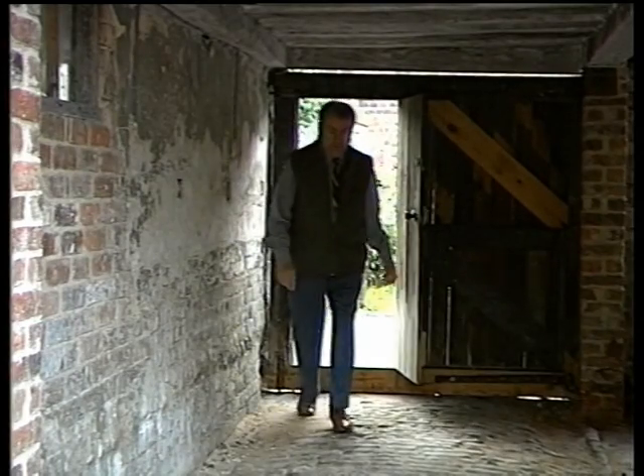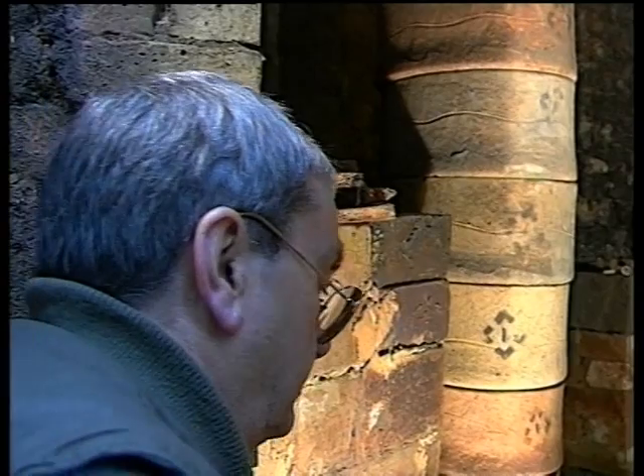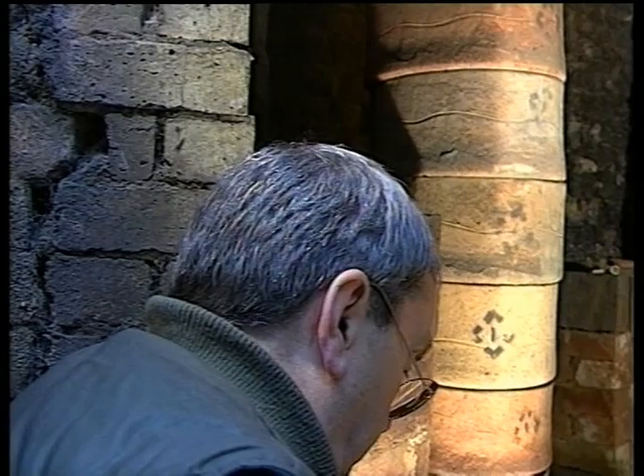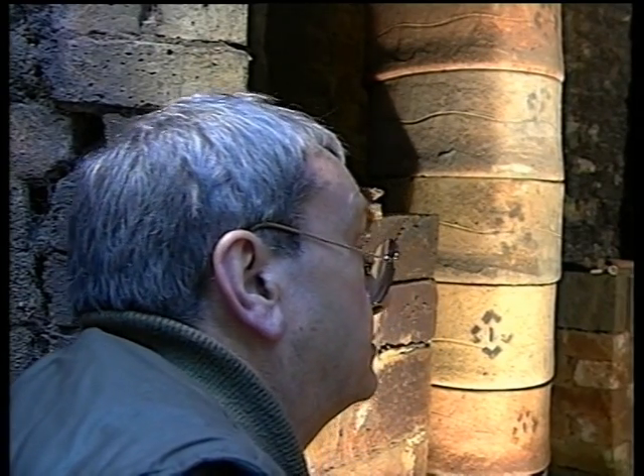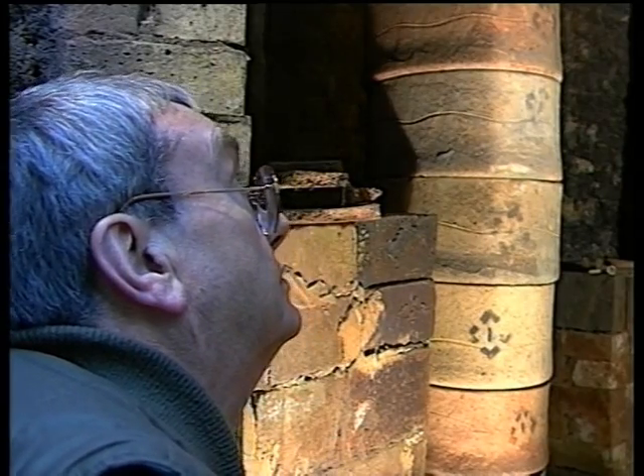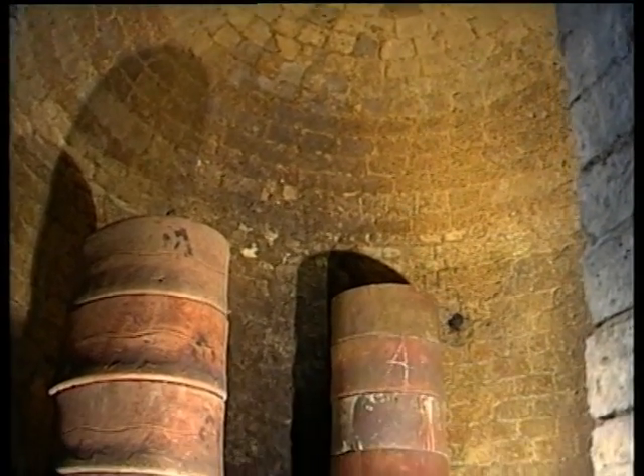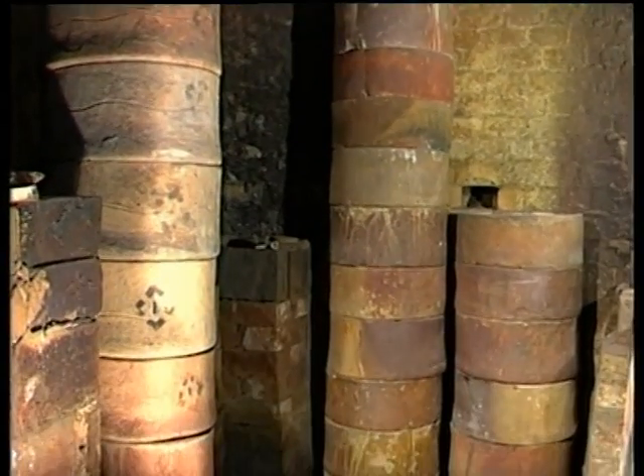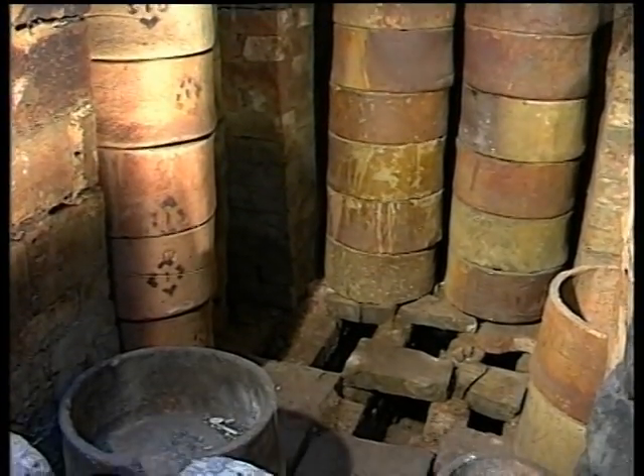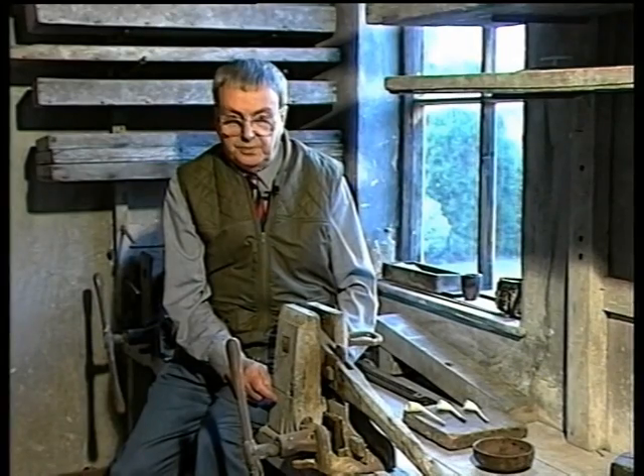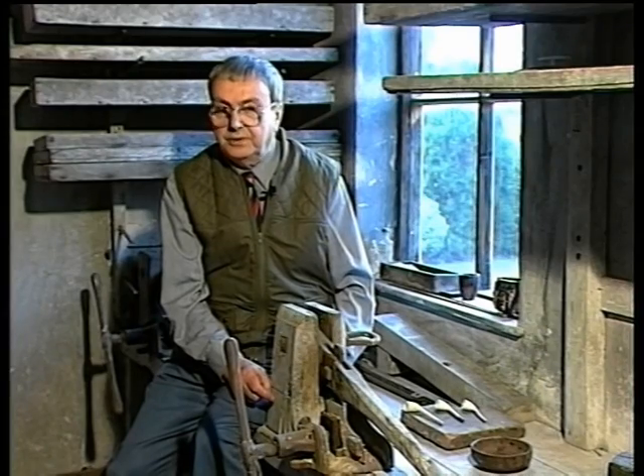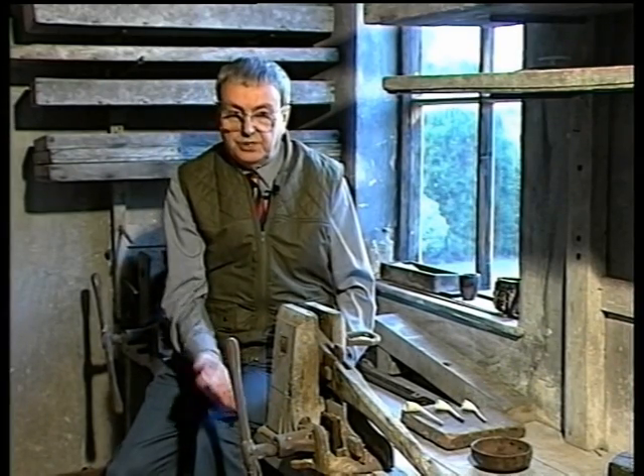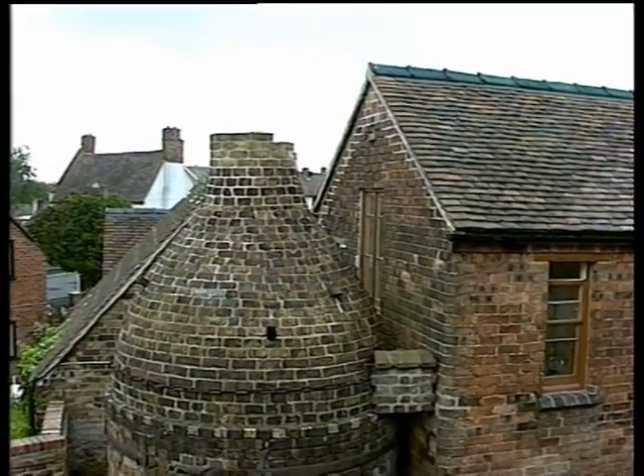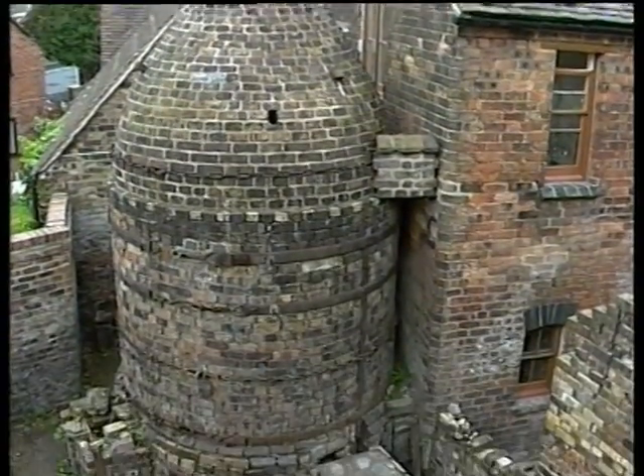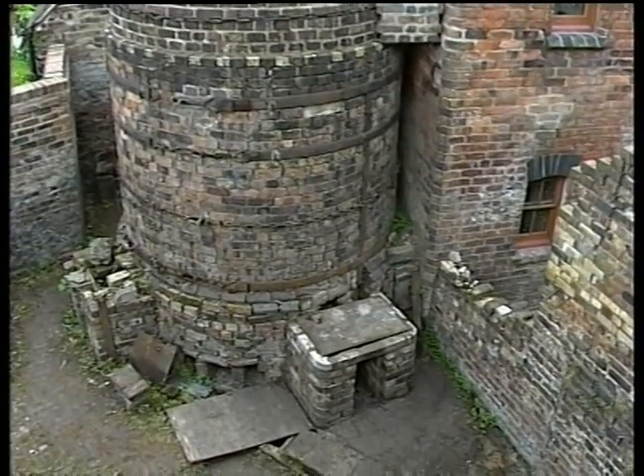Ivor Southern, Harry's son, still lives in Broseley and remembers his father's factory when it was working. The coal-fired bottle kiln built by Roland Smitherman in the 1880s was still used, and Ivor can remember helping with the firing. The big pipes were put at the top of the kiln, and the small ones down the bottom, because naturally there was less heat at the top. In that type of kiln, which was originally a bottle kiln, and then it was blocked off, the heat would start at the bottom, go to the top, and then come back down, and then back out through the flues. Keeping the coal burning during the firing sometimes called for drastic measures.